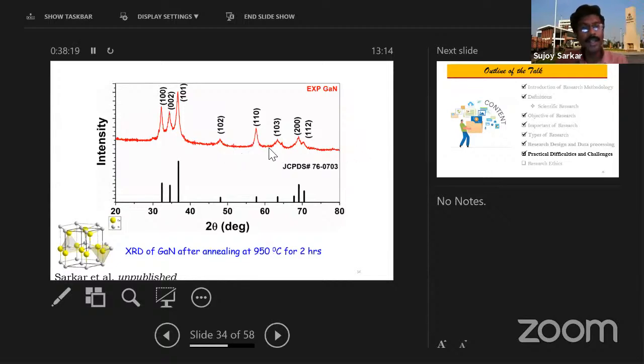We have not done the refinement of this one, but we actually analyzed this with the known data found in the literature. This is called the JCPDS file, which has XRD data for all kinds of known materials. So we are matching the data, and it's nicely matched with the wurtzite structure of gallium nitride.